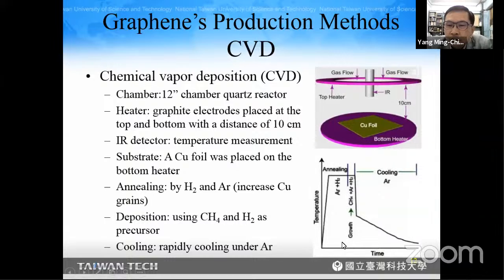And this figure shows the temperature profile of this process. The gases, methane and hydrogen, are used as the precursor, and they will deposit on the surface of this copper foil. And after a certain time, gases are injected to cool the system, so that on top of this copper foil, a few layers of graphene will grow on this surface.